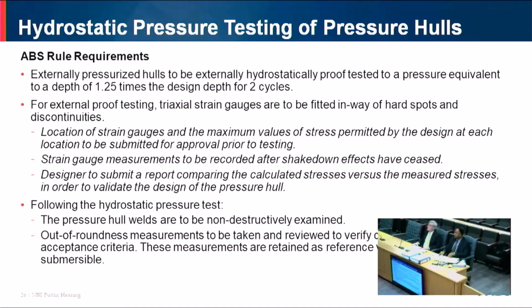So then once the hydrostatic pressure testing is completed, the designer will submit a report comparing the calculated stresses versus the measured stresses. There should be a good correlation. If there's not a good correlation, we'll ask the designer to justify what's happening. Why are the calculated versus the measured stresses varying, okay?